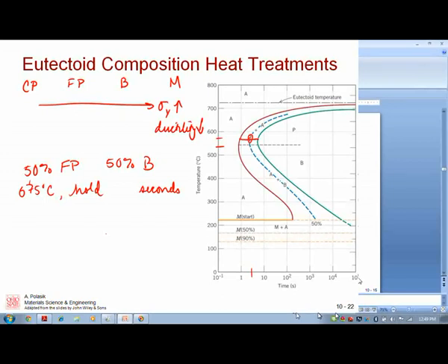change a little bit. Certainly the mechanical properties are always going to change with heat treatment, right? And so that's the other thing, is the material, same chemistry, change if we change the cooling path? Is it still the same material? To a materials engineer, no. And should be no to you, because it's going to have completely different mechanical properties. When we look at a material, if you're going to get a spec sheet for a steel, it's going to have information there about its processing history, because that is absolutely going to affect the microstructure and absolutely affect the properties.